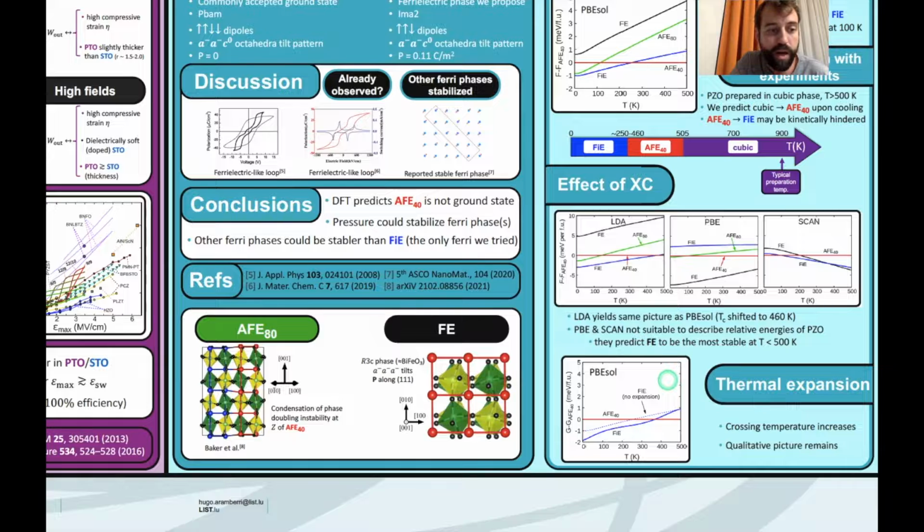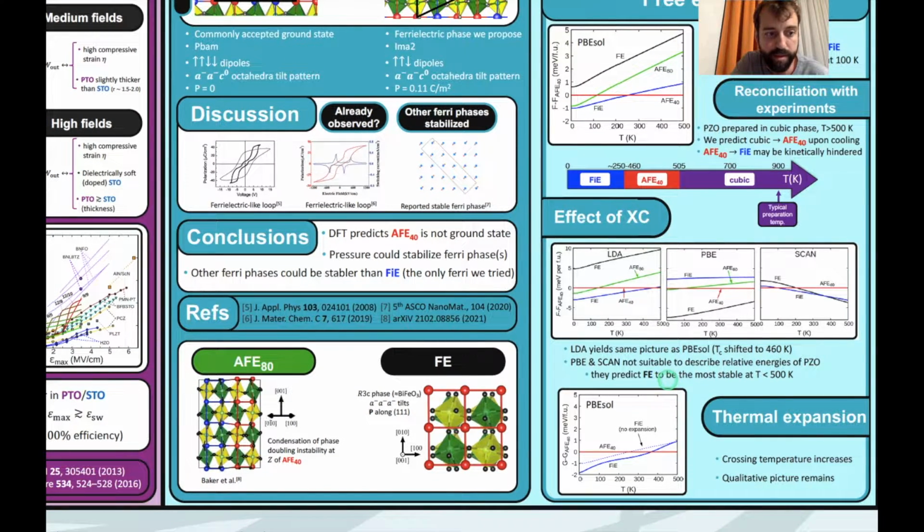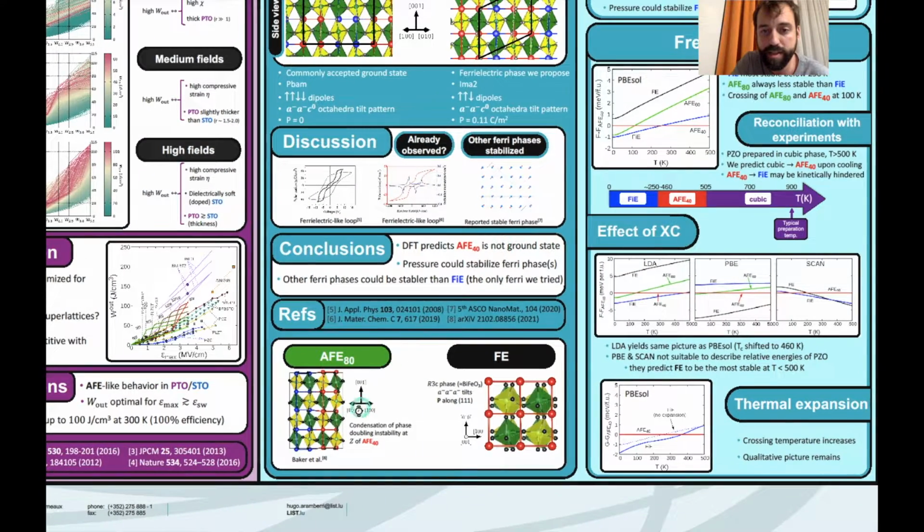So we discuss how our results can be reconciled with the experimental knowledge we have already of lead zirconate, and most importantly, we find that our results indicate that the ground state of lead zirconate may not be antiferroelectric, but rather ferroelectric instead.